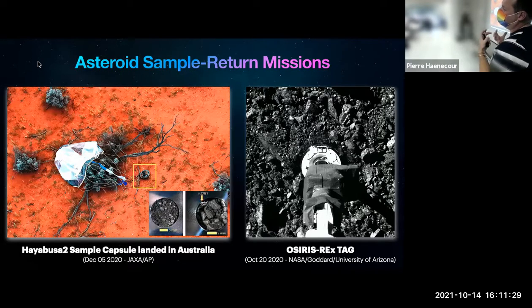Usually material from carbonaceous asteroids is very dark, looking almost like charcoal, and you can actually crumble it in your fingers. From some of the initial results we have heard, they have a really hard time even preparing samples, like making thin sections or mounting any of the sample, because just by trying to grab the particles, they break, and it's very friable.